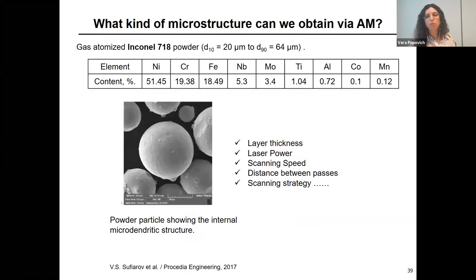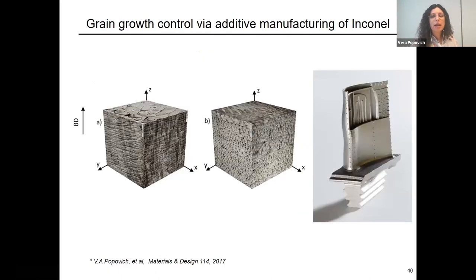What in our group we focused on, and I like to share this with my students for sure, because this is something that we have experience in and I have more knowledge on, is how we can grade the material with additive manufacturing technology, and what is relevant for this course is the high temperature superalloy Inconel 718. And we use powder. So this is an example of where you start the production of the material with the powder. It has a certain range, 20 to 60 microns. It depends on the supplier you get. And you start melting it layer by layer.